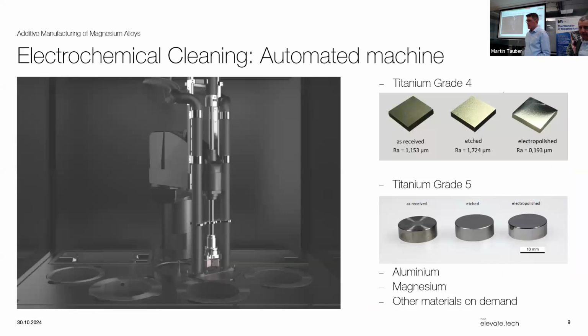The etch has received 1.1 micrometer and then etch 1.7 micrometer. What type of etching is that? The naming of it is probably a little bit confusing. As received, we have a corroded or passivated surface, and we took an etching process and we took away the passivation, and then the final process was the electropolishing. So basically the electropolishing is the most interesting part, where the surface is really shiny. Beforehand, the roughness even went up a little bit, but we removed the passivated parts.